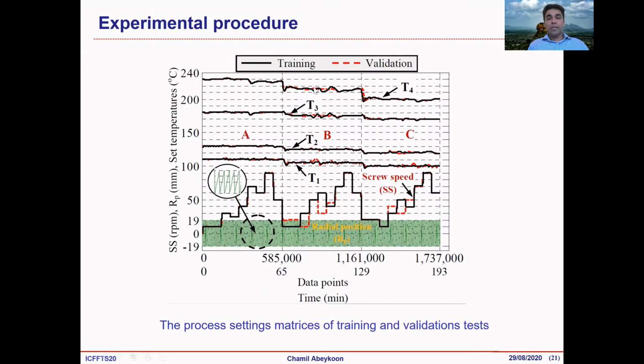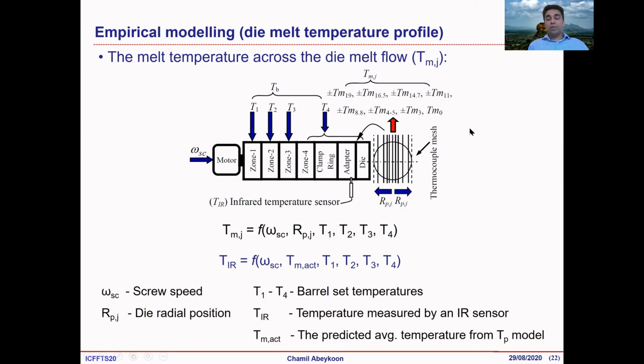So then we planned some system identification experiments covering the whole range of the extruder, from 0 to 90 RPM at a number of different temperature settings. This data set is more than 3 hours continuously. We collected the training and testing data sets, and after that we trained a model. Then we selected the model structure, which I was mentioning in the previous slides.